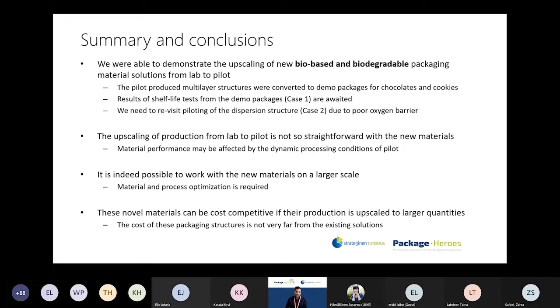We are still waiting for the shelf life test results, and we are planning to revisit the piloting of dispersion structure, as I already mentioned that we might have destroyed the fibrillated cellulose coating because we could see this poor barrier of oxygen. So we are planning to redo that with slightly thicker fibrillated cellulose coating layer, and that way able to reach the target barrier.